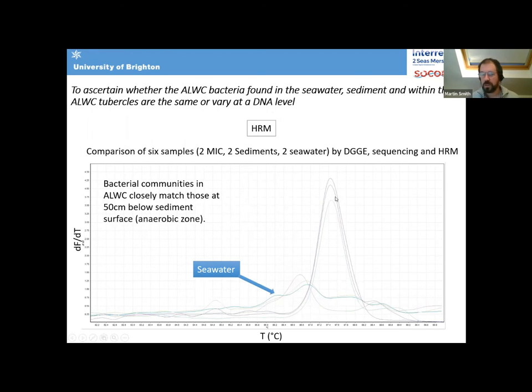the melting curves for specific DNA sequences, temperature along the base, change in fluorescence up the side. And we can see very clearly here, this individual peak here is from accelerated low water corrosion causing populations. So this is part of the dsrAB gene melting curve. In seawater, we don't see anywhere near as strong a development at that temperature peak. And in the sediments, shallow sediments match the seawater curve, but we see the same melting curve in sediments at 50 centimeters depth. So we're really building on this idea that the local sediment is the source of the causative bacteria. So we can identify a risk factor for marine infrastructure.